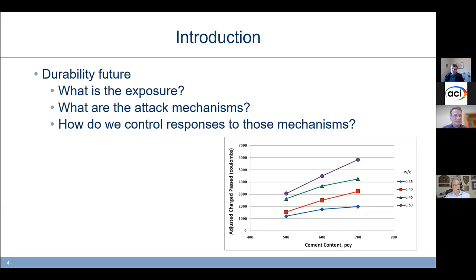This graphic is from one of my PhD students, where she made concrete with different cement contents and measured the rapid chloride test. Increasing cement actually made the rapid chloride numbers get worse. This is not entirely surprising because the rock or aggregate in the system does not pass electrical charge while the paste does. So the more paste we have in the system, the higher the rapid chloride number is going to be. The same data, if we run the newer resistivity test, shows exactly the same trends. So adding cement is not the answer in many cases.